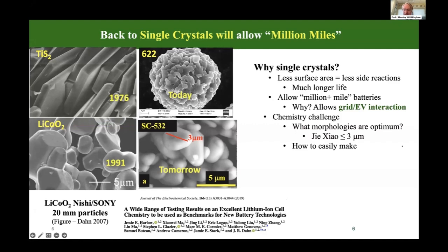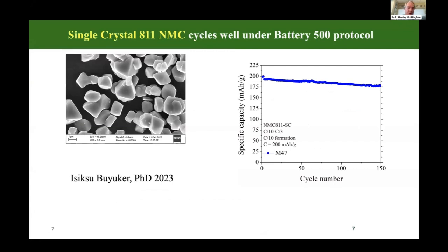The next question is, how can we easily make these in tonnage quantities? So we need the chemists to go back and really look at how to make these materials. So let's just look at some of the other options. First, single crystal, 80% nickel, fairly easy to make. These particular single crystals were cycled under what we call our Battery 500 protocol. This is using an ether-based electrolyte, C/10 charging, C/3 discharge, and you can see it's holding its capacity very well over 150 cycles, and it can go much further than that. The challenge of single crystals is it will not readily allow fast charging. So we'll have to have slow charging, but you'll have this option of a longer life.